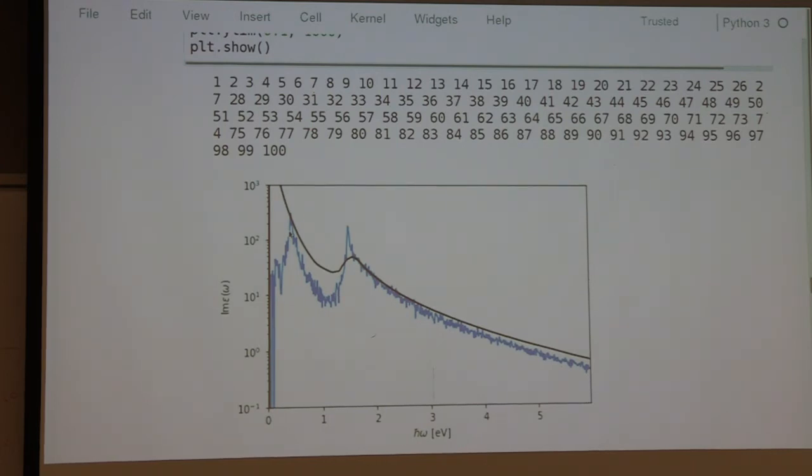So remember that this is only one of many mechanisms. This is the mechanism where you're only allowed to do vertical transitions. So what's happening here is you don't have that many possibilities for doing these vertical transitions. So the next best thing, which is using a phonon to pick up momentum, becomes important. And as you go close down to 0 energy, that becomes a dominant process, because you have a very large phase space for picking up momentum from a phonon and moving at the same energy, which you cannot do unless you had an external source of momentum.